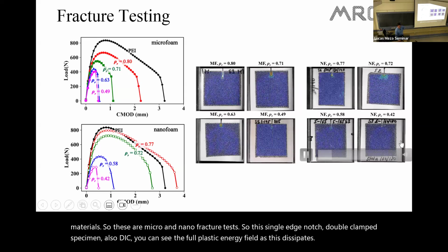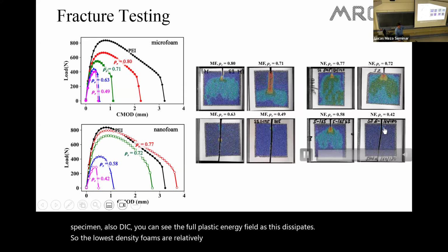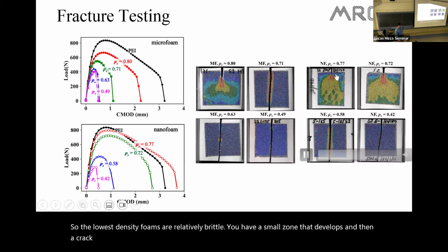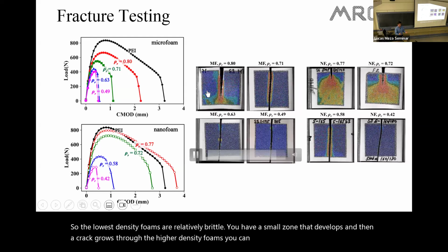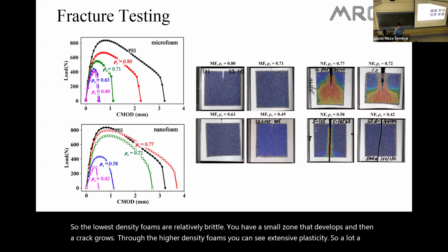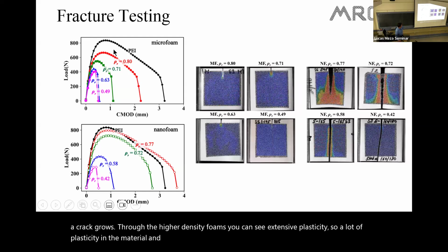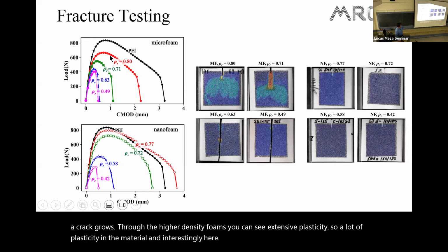So the lowest density foams are relatively brittle. You have a small zone that develops and then a crack grows through. The higher density foams, you can see extensive plasticity. So a lot of plasticity in the material. And interestingly here, PEI is this curve in black.